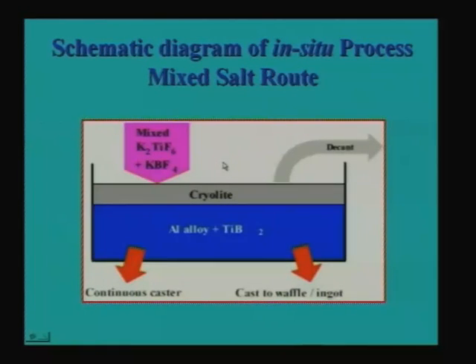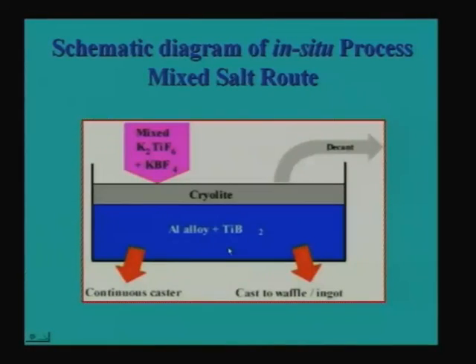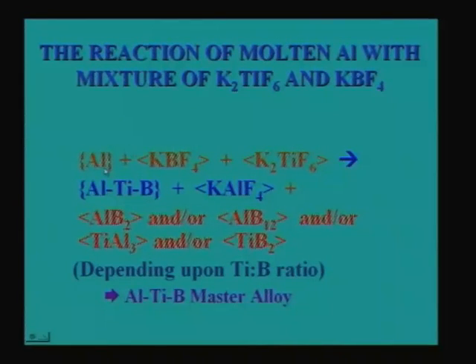And the other route is what we just started to introduce in the last class, what is called the mixed salt route. That means instead of making separate master alloys, one can directly add both the salts into the liquid aluminum at about 750 or 800 degrees centigrade and make these composites. If you look at the reactions involved, you take liquid aluminum, add KBF4 plus K2TiF6 together, then boron and titanium come out of these salts and go into the liquid aluminum and make a liquid aluminum solution with titanium and boron.